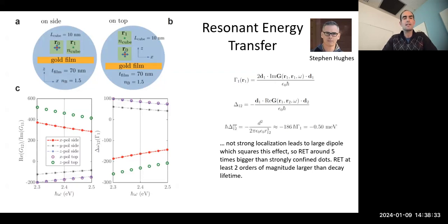There are a lot of different ways these quantum dots can couple to each other. They can couple by actually transferring electrons, by some charge interaction between electrons - there could be a tunneling process, a charge related process, or resonance energy transfer, which is what we observe here, where you have two dipoles and in the near field one emits and transfers its energy to the other. If that happens coherently, it transfers back and forth and you get splitting. That's the type of process you expect when you have degenerate dipoles.